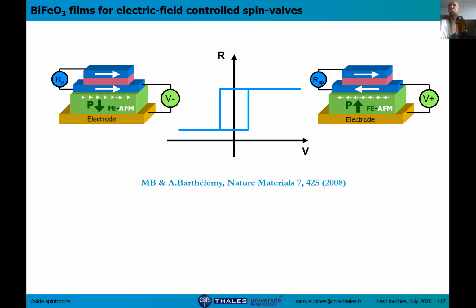And then if you make a superlattice of bottom electrode and ferroelectrics, with different tunnel junctions in series, I think it may be difficult to disentangle the switching properties of each junction in the series. But using a ferroelectric superlattice as the tunnel barrier could be interesting. I don't think people have done that really. Maybe by layers, with STO for instance, but not a superlattice.